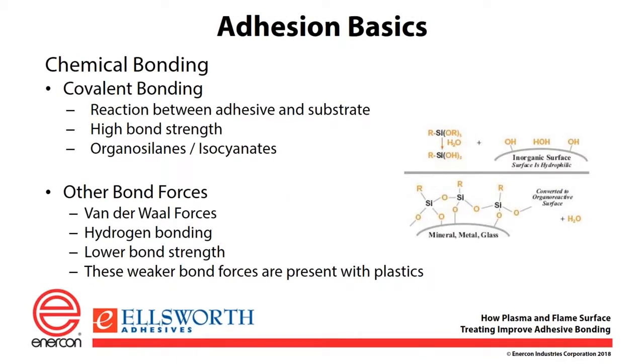In order to get adhesion to a substrate, you need bonding. We'll talk about basically covalent bonding, which gives very high bond strength if you can get covalent bonds. This is an actual reaction that occurs between the adhesive and the substrate. Some common ways to accomplish this for formulators of adhesives and coatings is to use organosilanes in a material, where the organosilane will react with the hydroxyl functionality on the substrate, assuming there's hydroxyls present, and the other portion of the organosilane will bond into your adhesive or your coating.